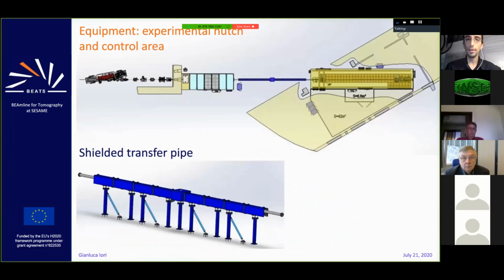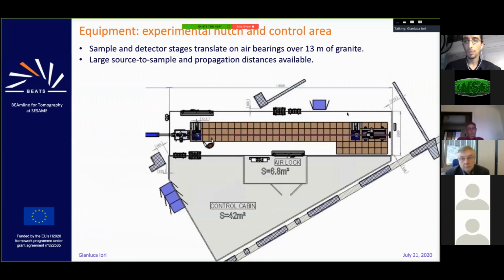After the optics, there is essentially just a shielded pipe that takes the beam to the experiment. And this is a diagram of the experimental hatch. This is a 14-meter long hatch where in brown you see granite. These are granite tiles covering 13 meters of the hatch. This is a very smooth floor, prepared so that the equipment, the sample holder and sample manipulator, can be displaced along the granite to work with different propagation distances between the source, the sample and the detector. As I explained, this is very important for phase contrast applications.